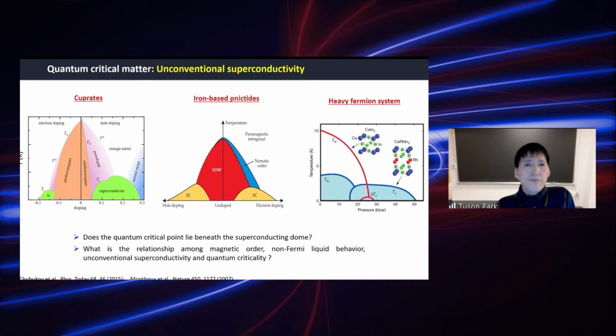Experimentally, unconventional superconductivity has also been observed in the vicinity of the critical point. Like in the high-Tc cuprates, a dome of superconductivity appears in the vicinity of the magnetic critical point, and iron-based pnictides also show these nice domes, for both electron doping and hole doping, and also the heavy fermion compounds under high pressure also show superconductivity. However, the presence of the quantum critical point beneath the superconducting dome is still an issue, and also the precise relationship among magnetic order, non-Fermi liquid behavior, and unconventional superconductivity is still controversial.